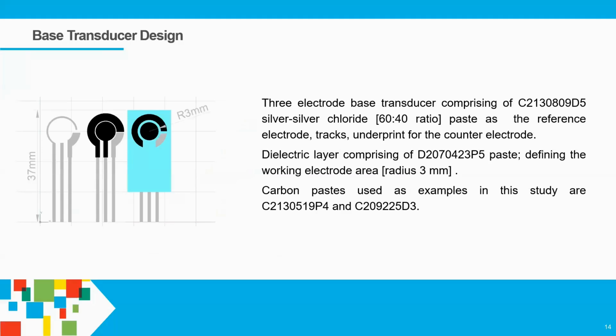So what we're trying to do is present the data in a different way. And the first thing we do is we tell them what design we're using. And if they want a CAD drawing so they can use this design for their initial experiments, we're happy to give it to them. We tell them what materials are used. So we've got silver chloride, which is used for the reference, and also the conductive tracks, and also a conductive track under the counter electrode. We tell them which dielectric. So if they have any questions, especially about the hydrophobicity of the dielectric, we tell them everything. The only thing we're going to vary in our experiments is the carbon.